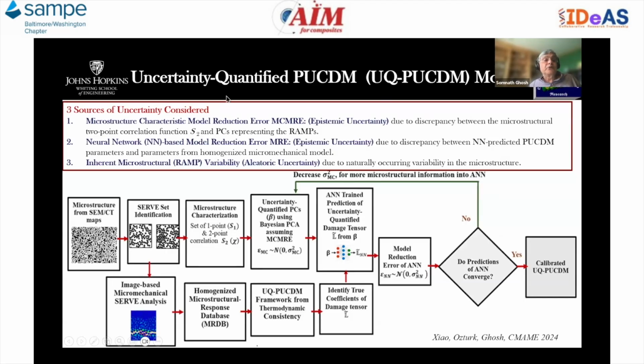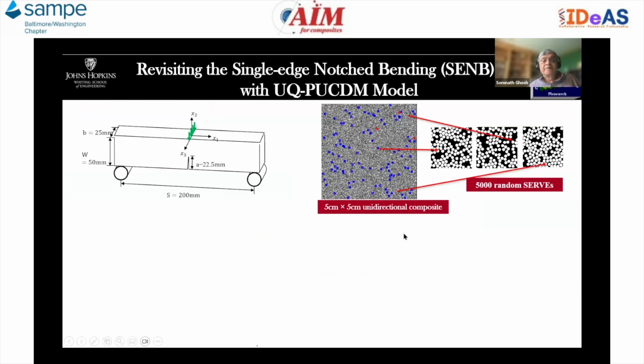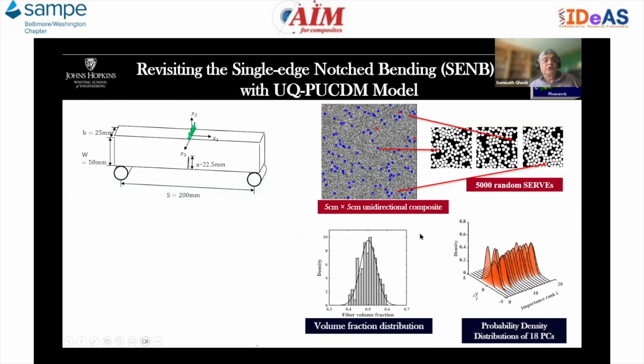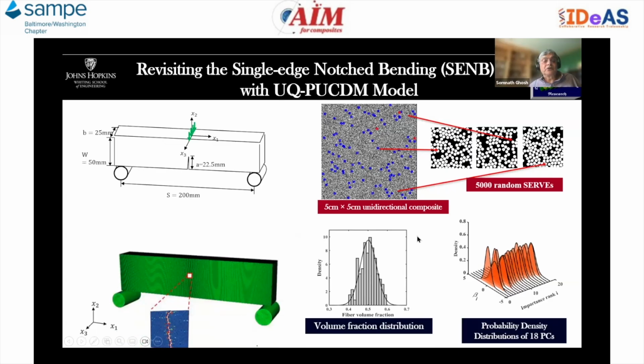with the UQ framework, uncertainty quantification, that takes care of three uncertainties: the epistemic uncertainty of microstructure characteristic model reduction error, also the epistemic uncertainty of neural network based model reduction error, and then the aleatoric uncertainty of inherent microstructural variability. So all three of them. And these correspond to the outcome of this uncertainty quantified PUCDM models.